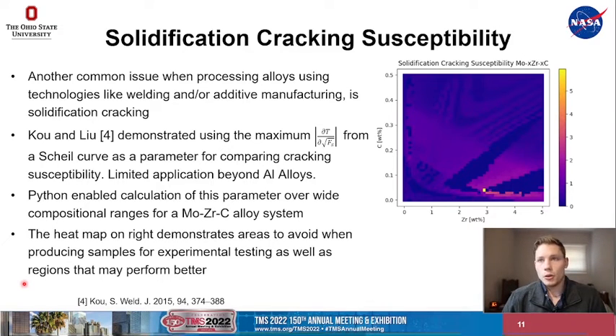We use Python in order to calculate this wide range of compositional space. And the goal of this is that the map would show you areas of compositional space where you would likely have high solidification cracking susceptibility. This would then be able to inform you in the lab when you're experimentally producing alloys of compositional spaces to avoid in order to avoid solidification cracking.